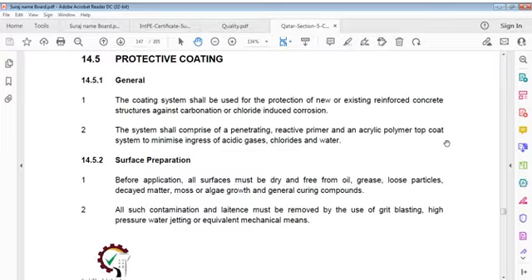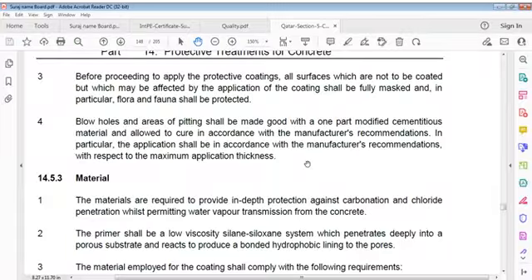decayed matter, moss or algae growth and general curing compounds. All such contamination and laitance must be removed by use of grit blasting. All surfaces which are not to be coated but which may be affected by application of the coating shall be fully masked, and in particular flora and fauna shall be protected. Blowholes and areas of pitting shall be made good with one part modified cementitious material and allowed to cure in accordance with manufacturer's recommendations. In particular, application shall be conducted in accordance with manufacturer's recommendations.